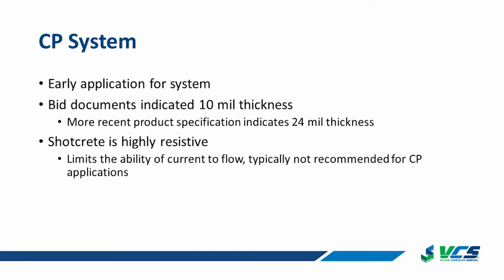One thing too, I mentioned shotcrete. Shotcrete is really highly resistive because it has a lot of silica fume in it. So whenever you're doing cathodic protection and there's shotcrete repairs, that brings a little bit of alarm to a CP person, because we've got to push current through the concrete. If we have really high resistive concrete, that'll affect the performance and current flow from that anode, because of the high resistivity of that material.